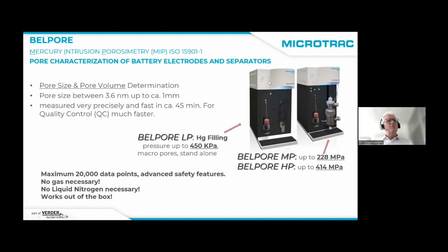So with this equipment we determine the pore size and pore volume, with pore sizes in the range of 3.6 nanometers up to about 1 millimeter. The measurement is pretty fast, up to about 45 minutes. We can get a complete measurement cycle with all information about the pore size distribution and the pore volume. We can measure up to 20,000 data points. We don't need any gases, no liquid nitrogen, so it simply works out of the box.